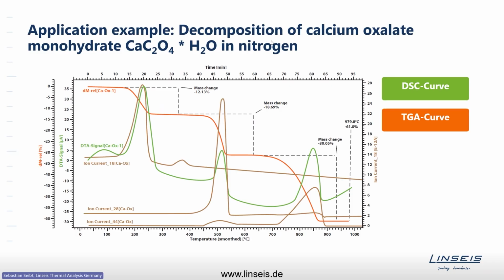The next example is the decomposition of calcium oxalate, which we use as a more or less reference material for our STAs. In this case, a mass spec was coupled, so we also monitored, by mass spec, the mass of water, the mass of carbon monoxide and of carbon dioxide to show you what comes out here. Again, the orange curve shows you 3 mass loss steps. The green curve is the DSC signal, and the brown curves here are the masses of different AMU lines, especially of water, carbon monoxide, carbon dioxide.